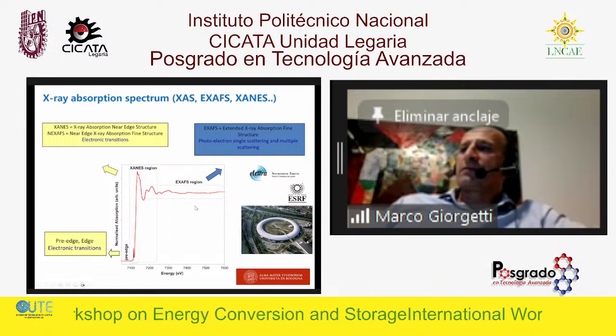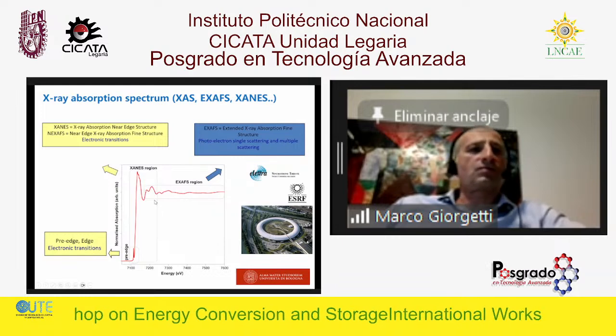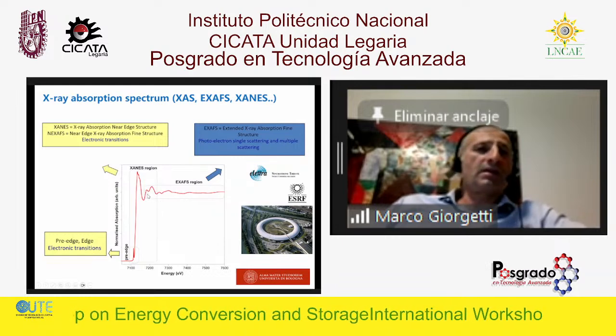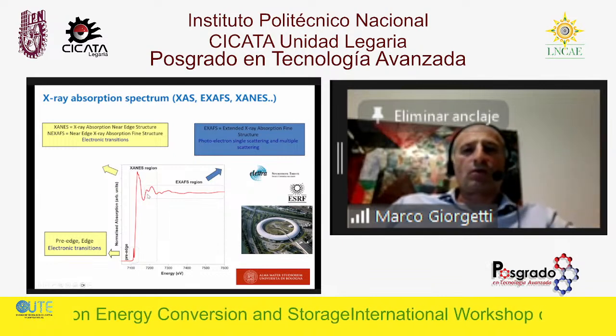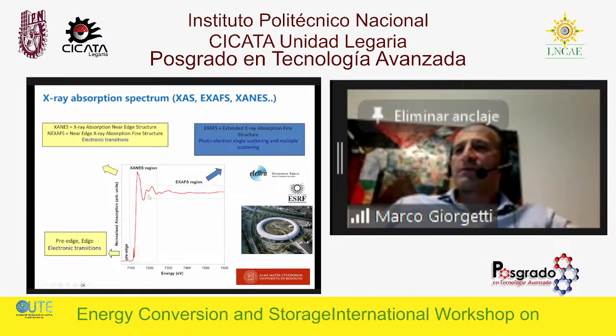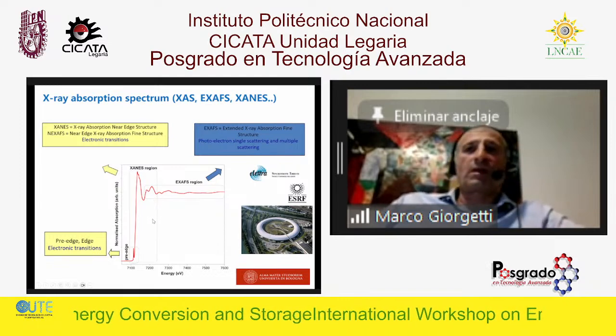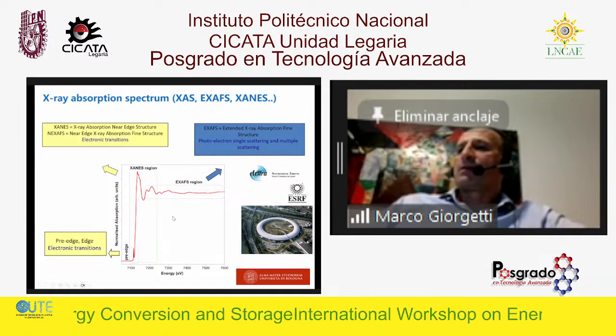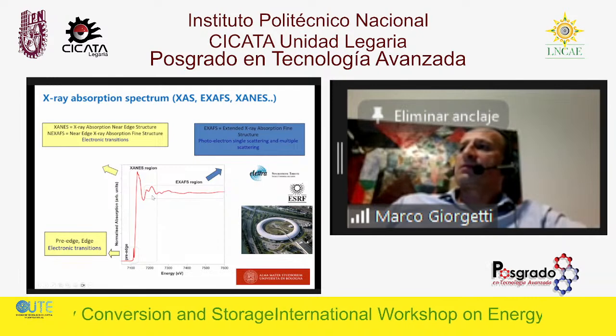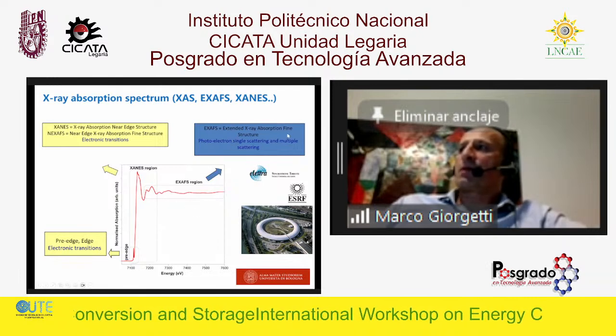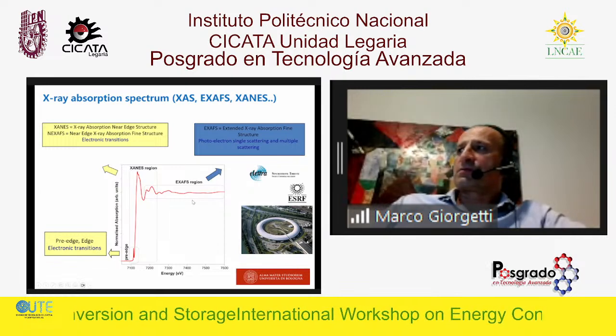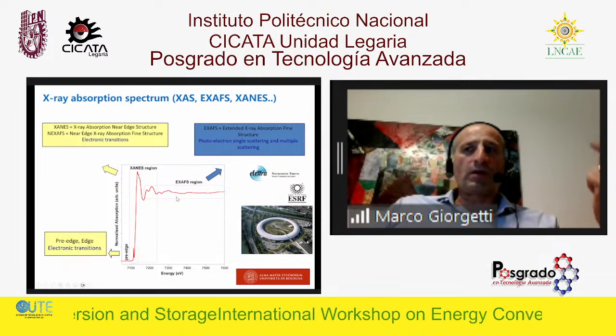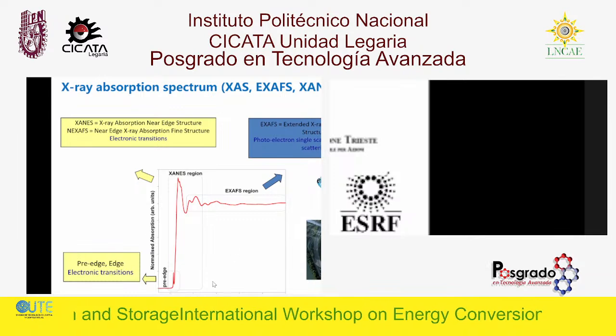And what is also interesting is this kind of oscillations. Why do we have these oscillations? We have oscillations because basically we have an atom where we create a core hole, and it is surrounded by some other atomic sites, some other atoms. So the atomic coordination can give these oscillations. They are called extended X-ray absorption fine structure, EXAFS, and they are due to photoelectron single scattering and multiple scattering. The photoelectron is the one created by bombarding the material with X-rays. So basically, three regions. One is more for electronic information, the other for structural information.